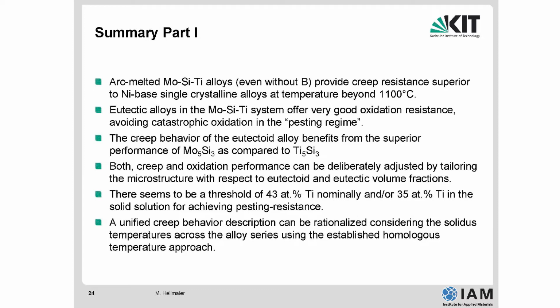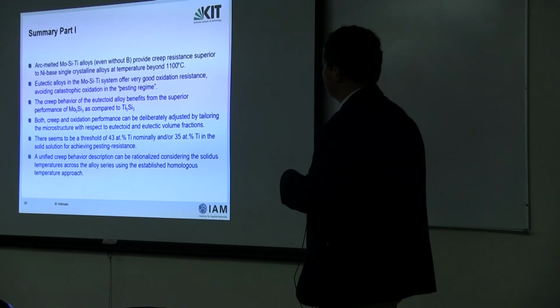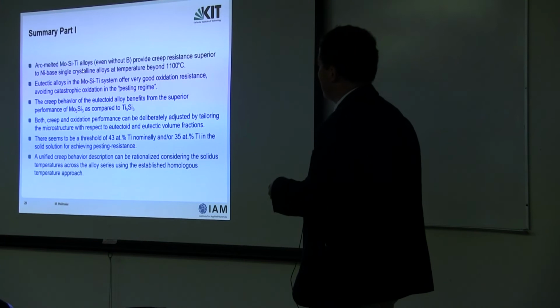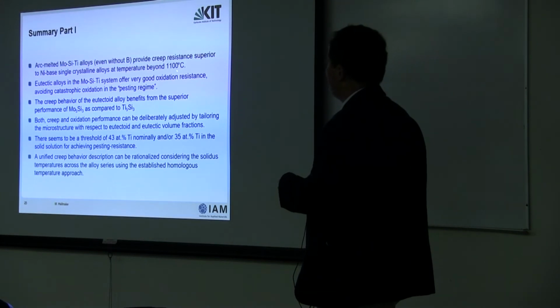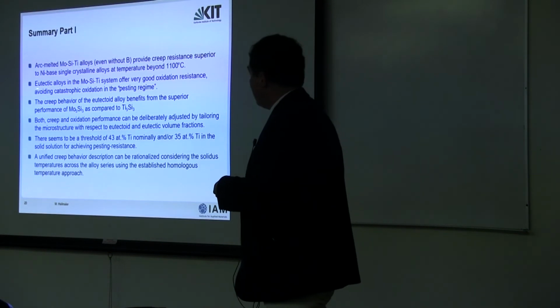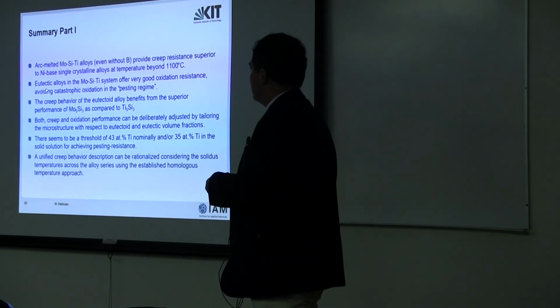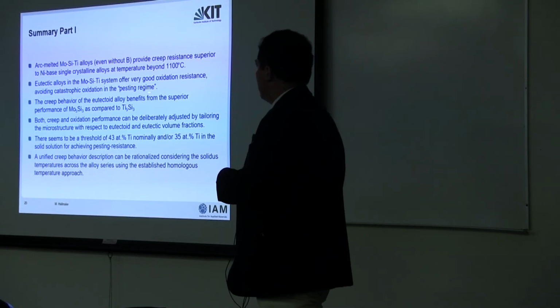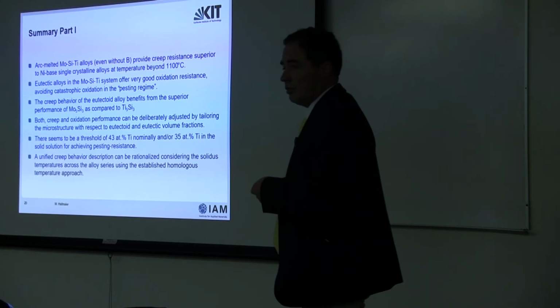Okay, so summary of part one. We did arc melting, so this is a simple process. We have polycrystals, no single crystals, like in the case of nickel-based superalloy. Nobody knows what happens when we try to melt single crystals, but polycrystals are simply arc melted. With or without boron, they provide creep resistance superior to nickel-based single crystalline alloys at temperatures beyond 1100 degrees Celsius. The eutectic alloys offer very good oxidation resistance. They avoid catastrophic oxidation in the pesting regime.